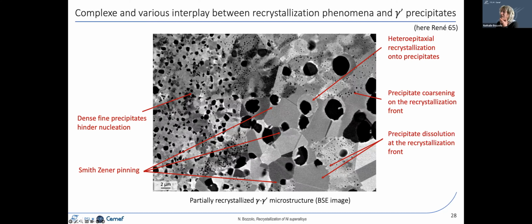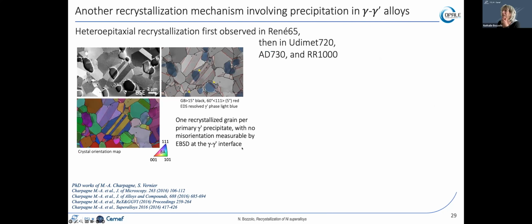Another phenomenon we have seen in these alloys is no longer a simple recrystallization phenomenon, but a combined phenomenon, combining phase transformation and recrystallization. We call it heteroepitaxial recrystallization, and you will better see what I mean on this page here. So here you have a gamma prime microstructure, which is partly recrystallized. Here you very clearly have a primary gamma prime precipitate, a large gamma prime precipitate, which is inside a recrystallized grain. If you go to the orientation map down here, you can see that the precipitate has the same orientation as the matrix grain. And even the twin, which is crossing the grain, also crosses the precipitate.